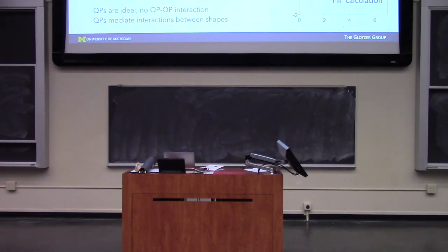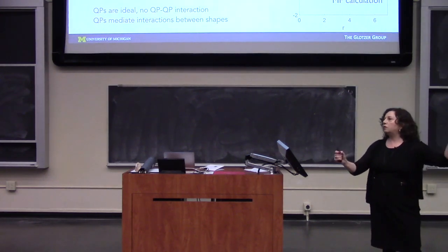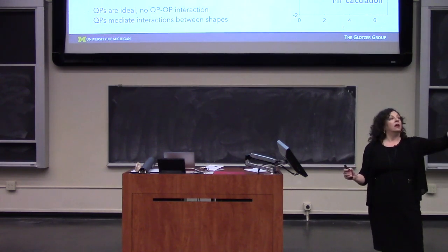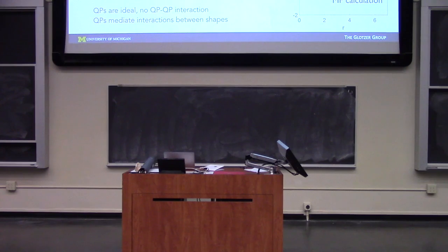That's what we're doing, and I'll just mention another thing T did. He said, once we have these little particles, we can write down a diffusion equation for them. You end up with a Smoluchowski equation, which, if you do this trick that Swanson did, that he found in some book, you can make self-adjoint, and then it looks like an eigenvalue problem. So, just to quickly say in 10 seconds what he did, you end up with something that looks like a Schrodinger equation. You get an interaction between, just like electron and nucleus, these fictitious quasi-particles and the shape. This sounds ridiculous, I understand that. I can't believe this works.